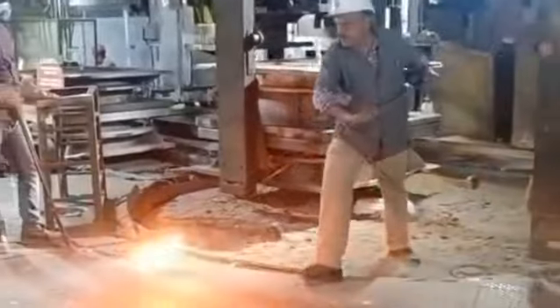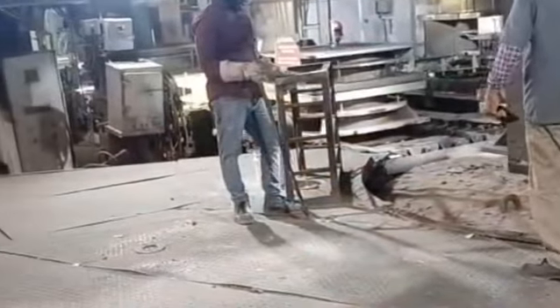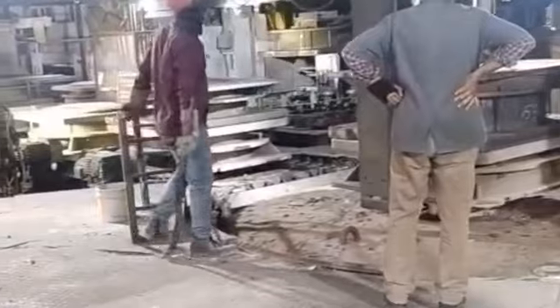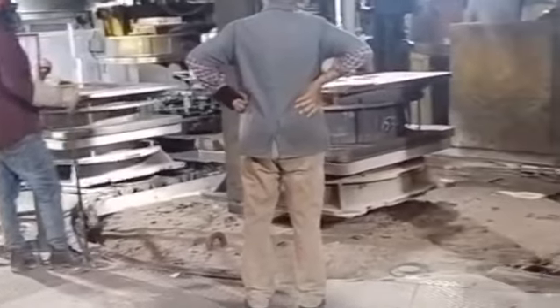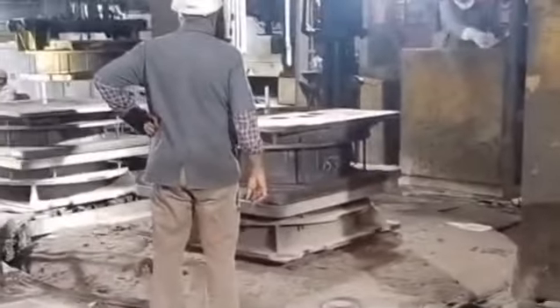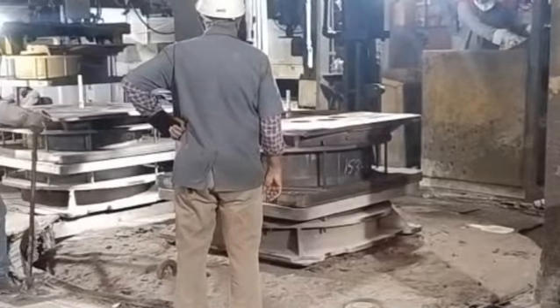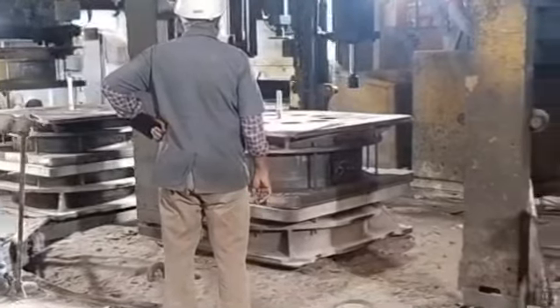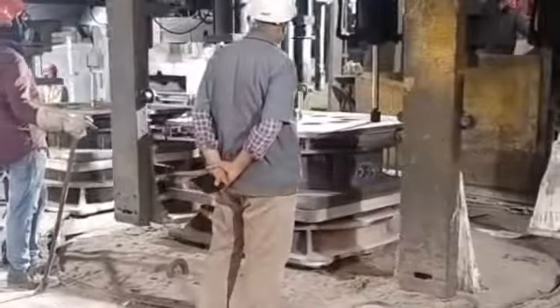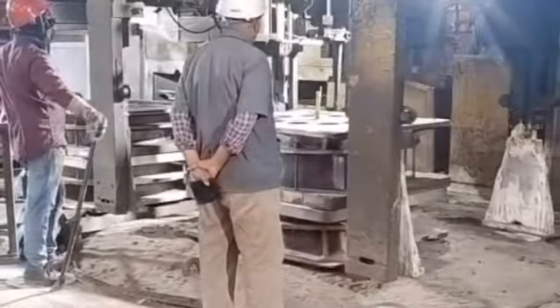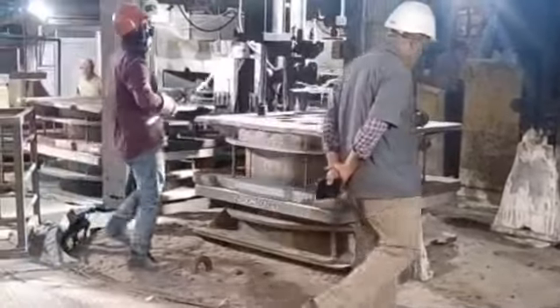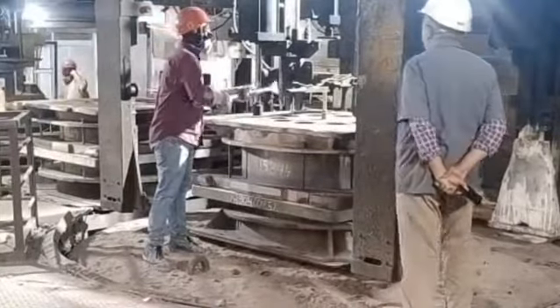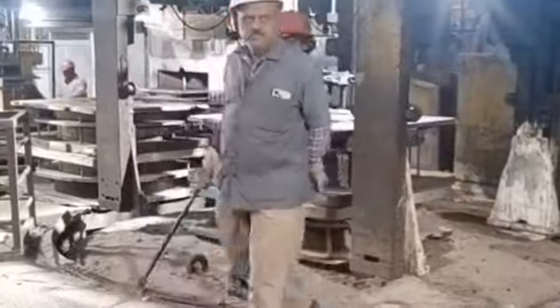Once the mold is prepared, it is subjected to 9 to 10 minutes of solidification. Solidification may be defined as allowing the metal to cool and solidify. After solidification, the cope and drag assembly is split and the cast wheel is obtained. The pouring of each wheel takes about 80 seconds. For one heat, 32 to 33 wheels can be casted. And a cope drag assembly can be used for 20 to 25 wheels.